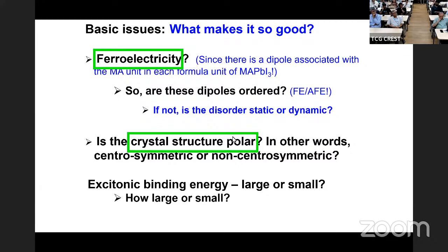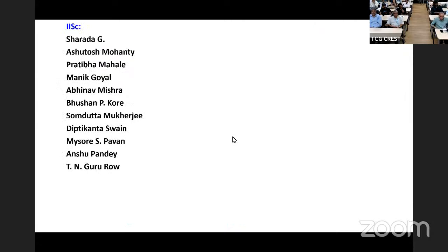Because if it is very strongly bound, then the electron and hole are not going to get separated and will not get the electricity outside. So it's a very important criterion to have the exciton binding energy small. The question is, is it small or large? Unfortunately, the estimates run from 2 to 100 milli-electron volts, which means that we don't have any agreement and one doesn't know what the excitonic binding energy is. These are the kinds of questions that we asked early on.